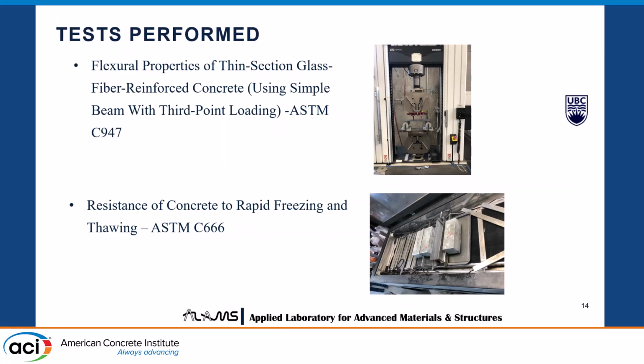And we also did a specific test for the GFRC, which is called the flexural properties of thin sections of glass fiber reinforced concrete using simple beam and third point loading. That is ASTM C947. This is basically a 4-point bending test. And finally, we did the freeze thaw test at ASTM C666, and we used procedure A.